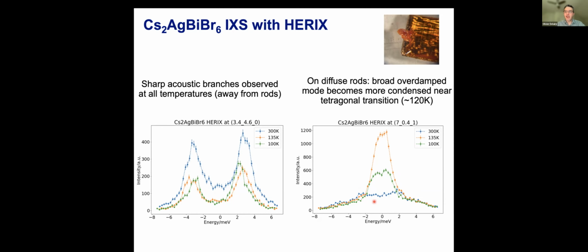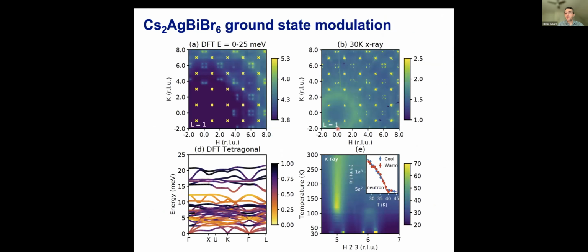Now, there's a further effect that we've discovered in this double perovskite, and that was quite surprising: the ground state is not what has been reported. It's not just the simple orthorhombic structure I showed earlier. We've found in the diffuse scattering data, as well as neutron diffraction, and as I'll show you with HERIX also, that there's a further modulation that appears below 40 Kelvin or so. And so you find these quartets of superlattice peaks systematically across reciprocal space. We can understand those in terms of a soft phonon in the tetragonal phase around the K point, as is shown in this calculation of the tetragonal phase. And indeed, we confirmed this based on the recent HERIX measurements. So let me show you this.